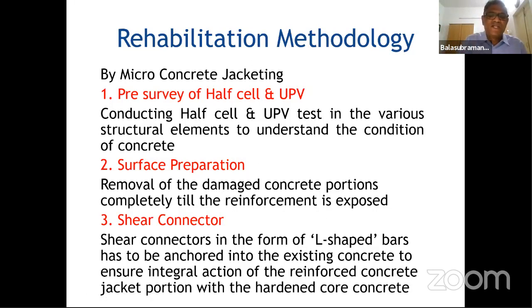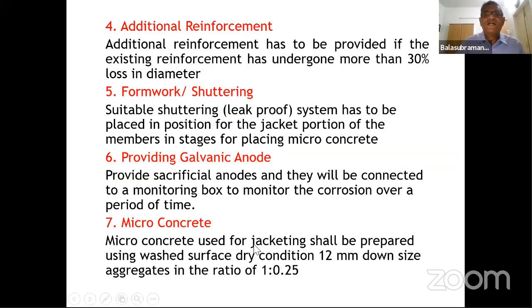In some of the ports where they did this shotcreting, we found that the shotcrete was coming out because there was no shear connector bonding the old concrete with the new concrete. So shear connectors have to be given. Then if the rod has undergone more than 30% loss in diameter, you have to put additional reinforcement, connect it to the shear connector, then give the formwork. And sometimes, we give sacrificial anodes, because it delays the onset of corrosion. That's a different topic by itself, so we'll not go into it. And then we put microconcrete.